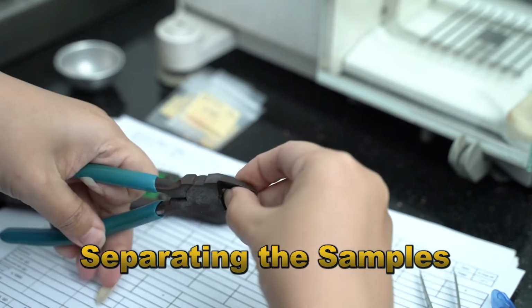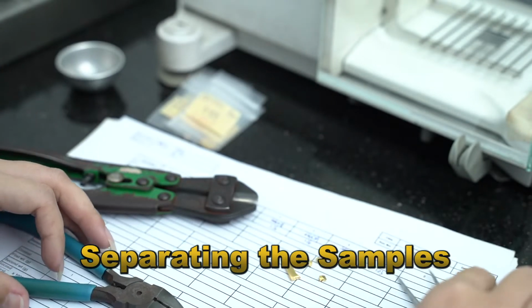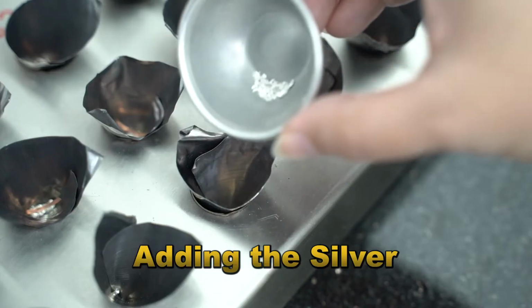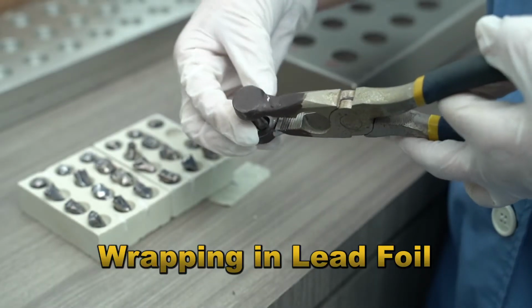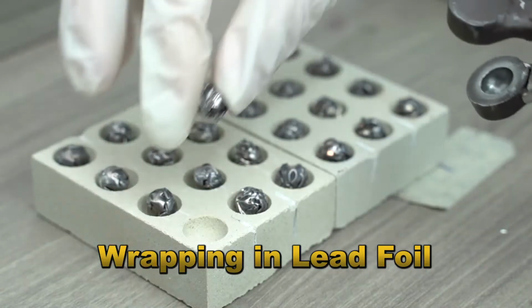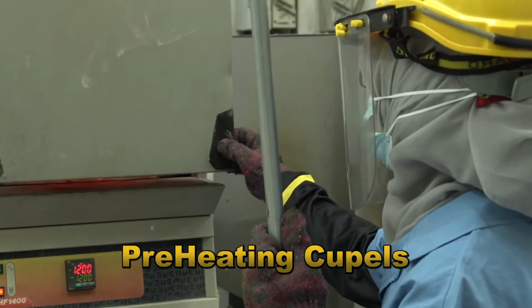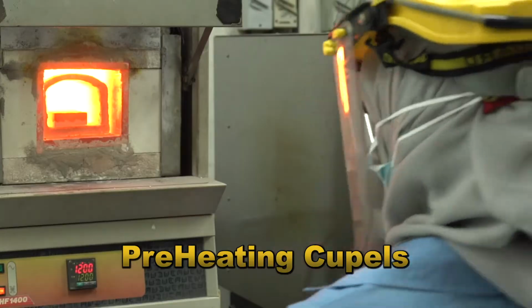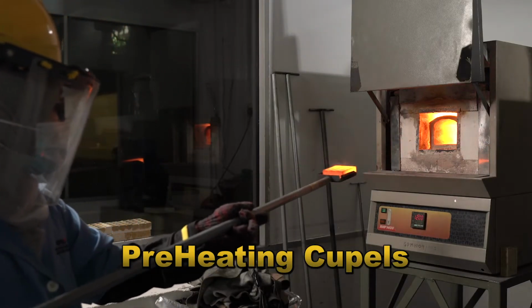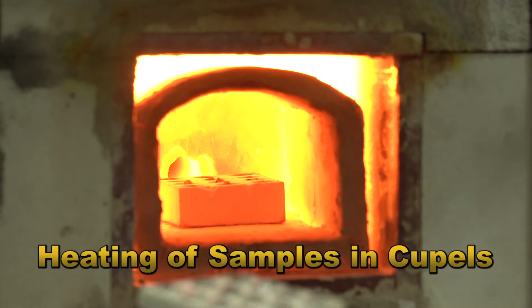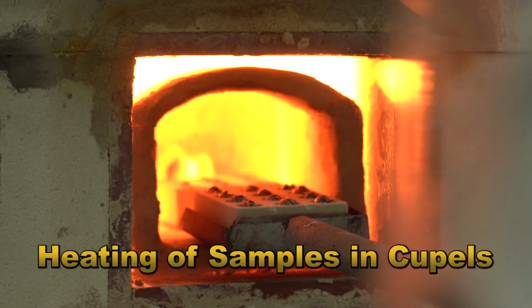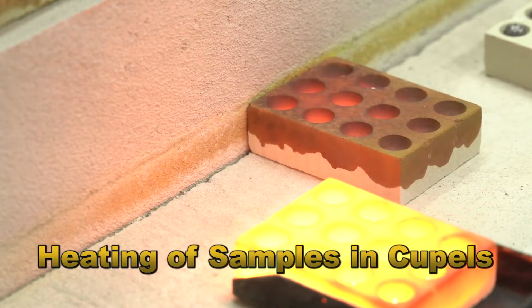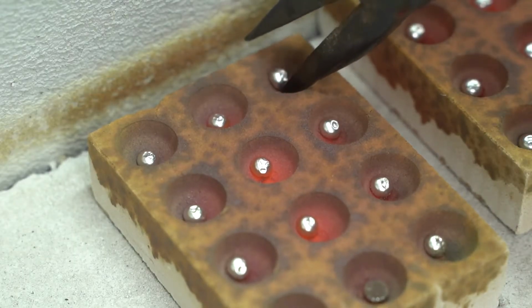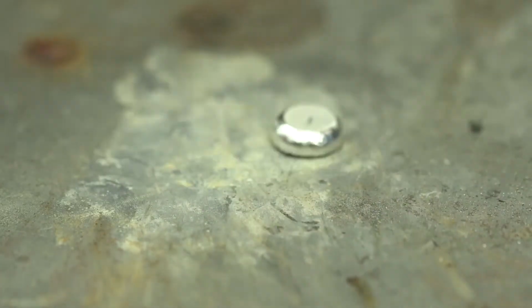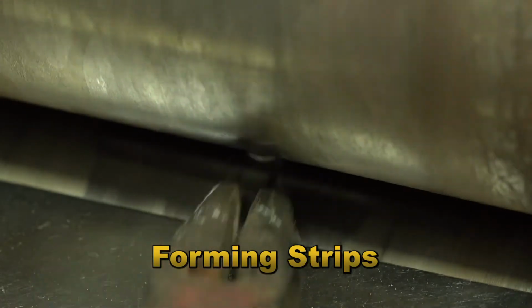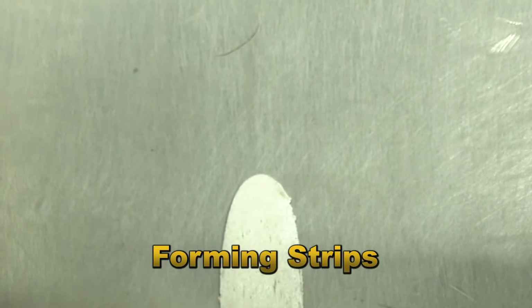This begins by taking a sample to be assayed, and the sample will then be further cut into 3 smaller samples. The smaller sample is weighed, then wrapped in lead foil together with silver and copper. Shallow porous cups known as cupels are preheated inside a muffle furnace at 800 degrees Celsius. The samples are placed in the cupel and inserted into the furnace to be heated at 1100 degrees Celsius. The samples are then cleaned, annealed at 800 degrees Celsius, and then rolled and formed into a strip form.